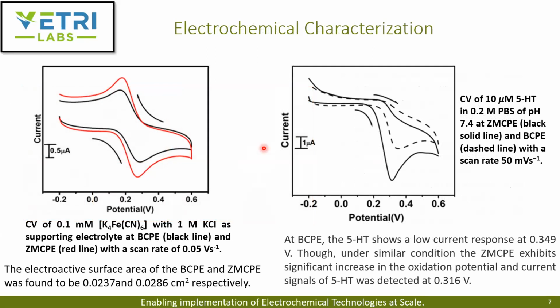So moving on to the electrochemical characterization. Before trying to detect serotonin, they used potassium ferrocyanide to calculate the electroactive surface area of the different electrodes. As you can see here, the black line is the bare carbon paste electrode, and the red is the zirconia modified carbon paste electrode. You can definitely see there is an increase in the current density.